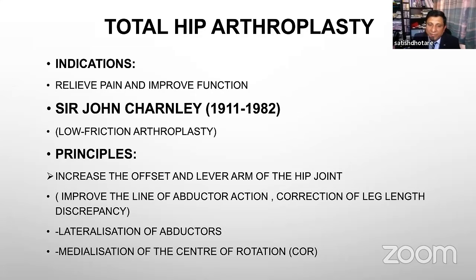So what was this low friction arthroplasty? Basically, he used a very small femoral head, which was 22.225. The polyethylene which he used, which was again initially first generation polyethylene, was not that great, but over a period of time the quality of the polyethylene has improved. However, while using the surgical intervention, which other principles did he use? The first principle was to increase the offset and the lever arm of the hip joint. So he used trochanteric osteotomy as a part of the approach, and that helped to improve the line of abductor action and to correct the leg length in the same sitting.